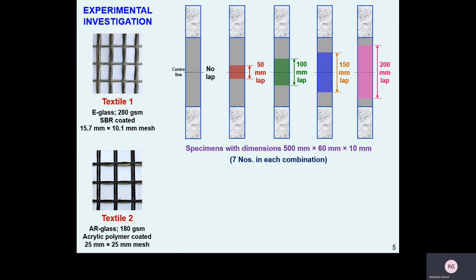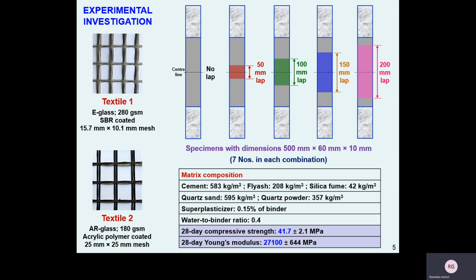The matrix used in this work comprised cement, fly ash and silica fume as part of the binder, quartz sand and quartz powder as part of the aggregates, and superplasticizer, all taken together at a water to binder ratio of 0.4. It resulted in a concrete with compressive strength around 40 megapascals.